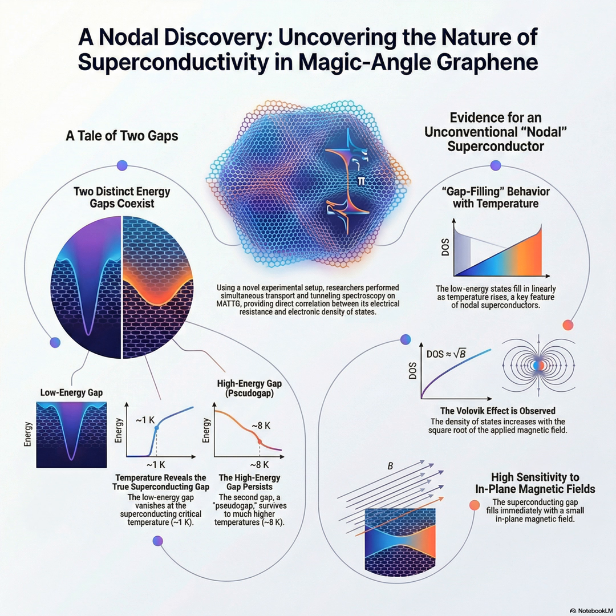Evidence 3 involved the in-plane magnetic field, parallel. So they ran a magnetic field parallel to the sheets of graphene. And what happened? The zero bias tunneling conductance immediately started to increase, even at very small fields, before it eventually saturated around 2 Tesla. Why is that immediate response to a parallel field so important? Well, in conventional s-wave superconductors, the energy gap is usually pretty robust against an in-plane field until the field gets strong enough to physically rip the electron pairs apart. But not in a nodal system.